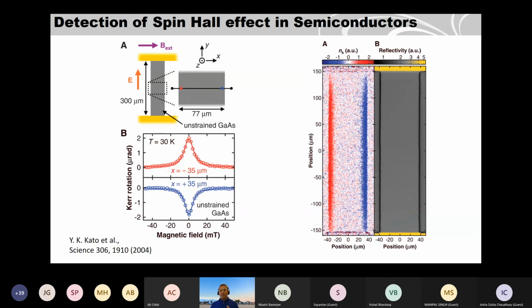Also, I have shown you in the metal case, there is a spin Hall effect. Actually, spin Hall effect was first realized in semiconductors like gallium arsenide in this paper. So they took a semiconductor, gallium arsenide, and applied a current here. And what they could see with this optical Kerr microscope is that one type of spin, this red one, is accumulated on the left side, and the other spin accumulated on the right side. So this is the real device picture as you see with the microscope. Okay, and this is the Hanle measurement. How this spin density you create depends on the magnetic field. So once you apply magnetic field, spins will dephase.